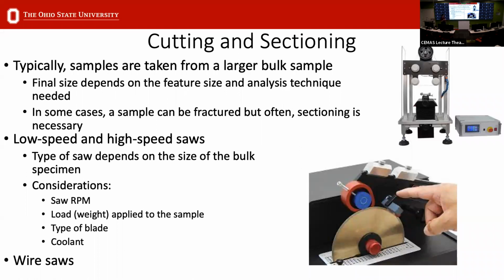There are dozens of different kinds of blades that are more optimal for something hard, like perhaps a diamond substrate, or if you're cutting something ductile, they make these wafering blades that are optimized for that. Likewise with load, if your sample is brittle, you don't want a high load on it because it could crack under the applied weight and under the sawing. And for cooling, you can usually use water for a lot of samples. If your sample is water sensitive, you can use various oils that are made specifically for cutting.